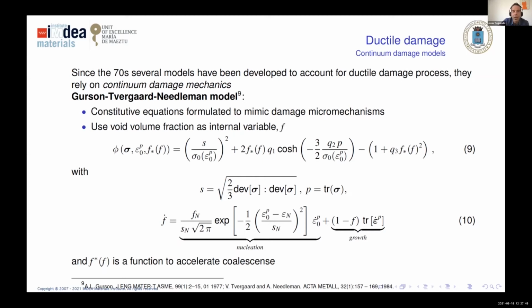In this case, we construct a constitutive equation that mimics the damage micromechanism. The damage micromechanism in ductile metals is the nucleation, growth, and coalescence of small microcavities that form a damage band that at the end converts into a crack. The Gurson model, which is very famous so I'm not going to insist on it, is just a yield or flow surface that introduces a dependency not only on the deviatoric stress, but also on the pressure through some volume fraction of porosity. The volume fraction of porosity evolves, like a damage variable, through nucleation and growth. With this model, we are able to predict the response macroscopically, but also to have an idea of the level of microscopic damage in terms of volume fraction of voids.